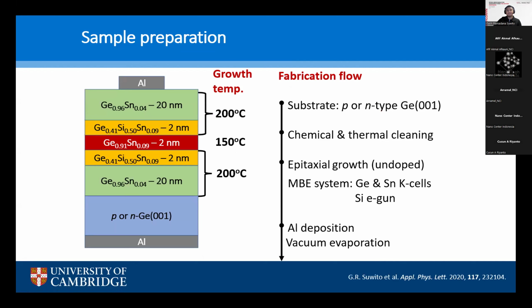We prepared two samples with different substrates, one P and the other one N. First we did chemical cleaning and thermal cleaning, and then we did MBE, and the temperature was varied between 150 and 200 degrees C. And then in the end, we deposited aluminum using vacuum evaporation.